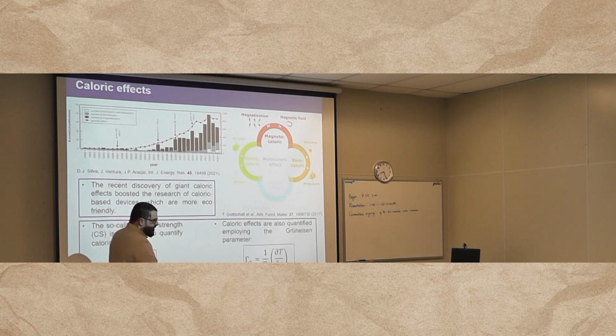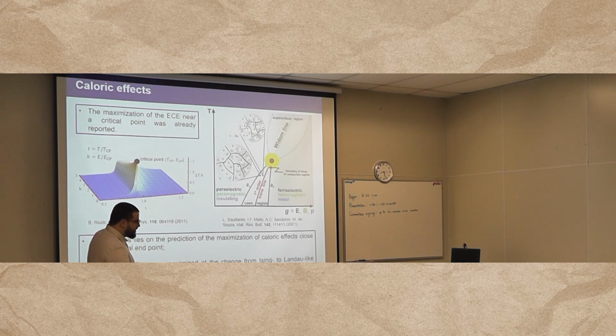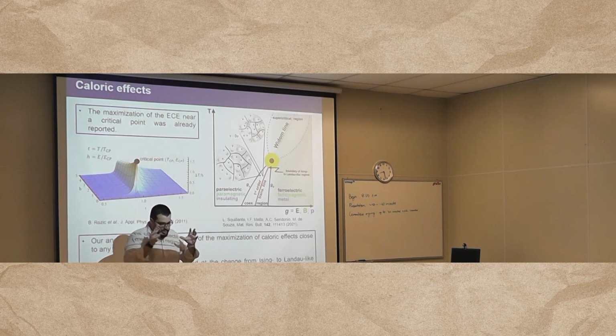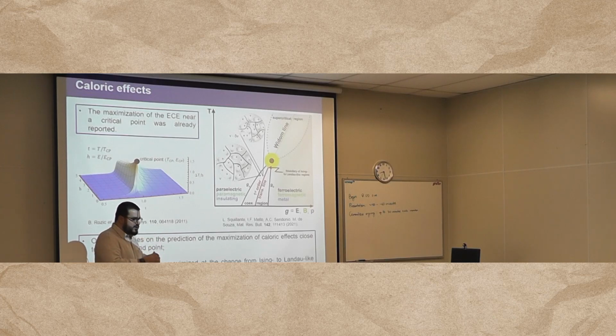Usually in the literature, how do we quantify if a material has large or small caloric effects? Usually it is how much the temperature is varied divided by how much you have to change the tuning parameter to achieve that variation of temperature. So, as I mentioned, the Grüneisen parameter also quantifies caloric effects, and there is additional information that can be extracted from this parameter because it is associated with the entropy, an aspect that is not covered here. So the maximization of the electrocaloric effect near a critical point was already reported. Here we can see that close to the critical point, the variation of temperature is maximized. But what we have done is, knowing that close to any finite temperature critical point we have an intrinsic entropy accumulation, and that this entropy is crucial for determining if the caloric effect will be large or small.